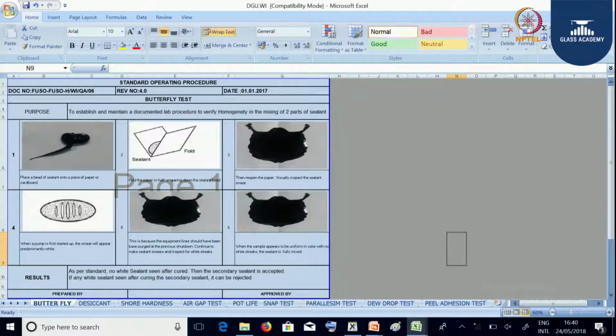Now let us take the insulating glass sealant. The purpose of doing the butterfly test is, since the secondary sealant is a two-part component, we need to maintain the homogeneity of the two parts. One of the tests used to check homogeneity in the mixing is the butterfly test. The procedure is: first we take a bead of sealant onto a piece of paper, fold it, and then try to open it.